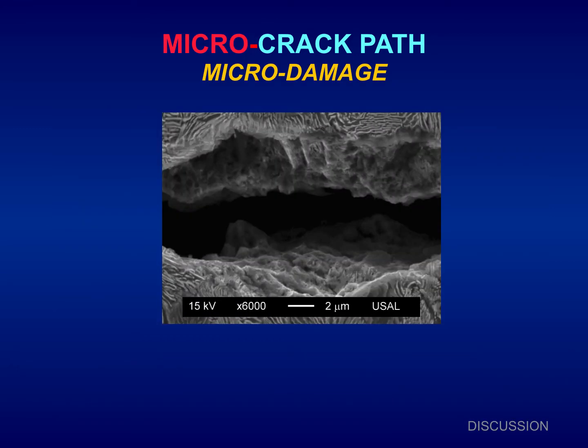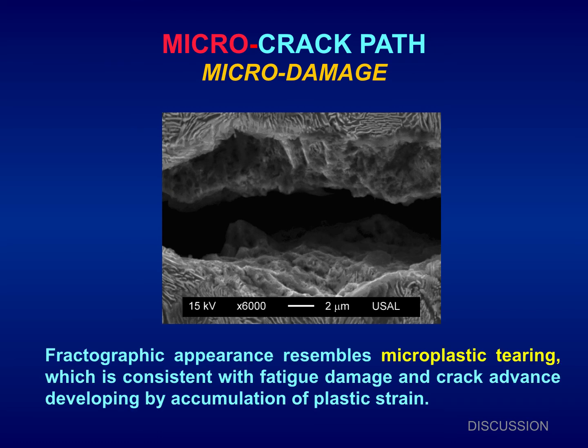With regard to the microcrack paths, we observe micro damage. Fractographic appearance resembles microplastic tearing, which is consistent with fatigue damage and crack advance developing by accumulation of plastic strain.